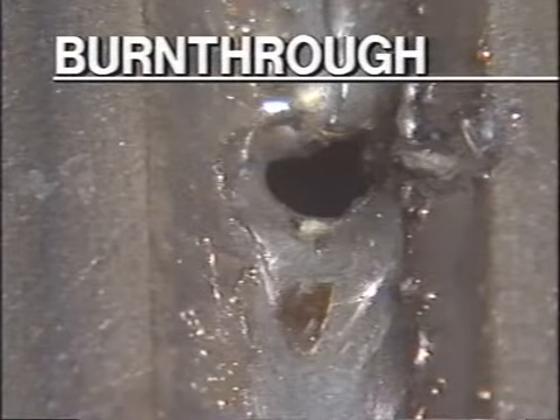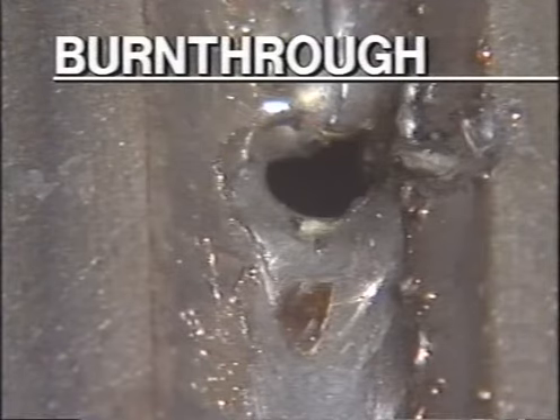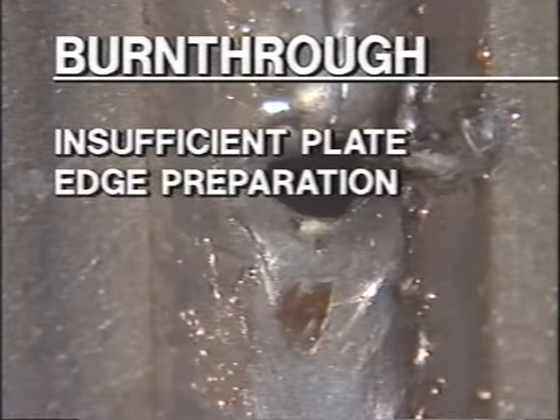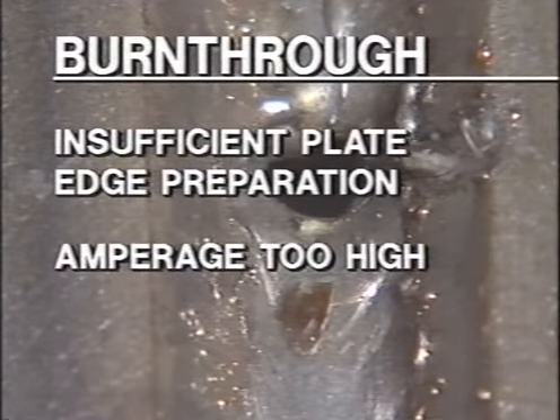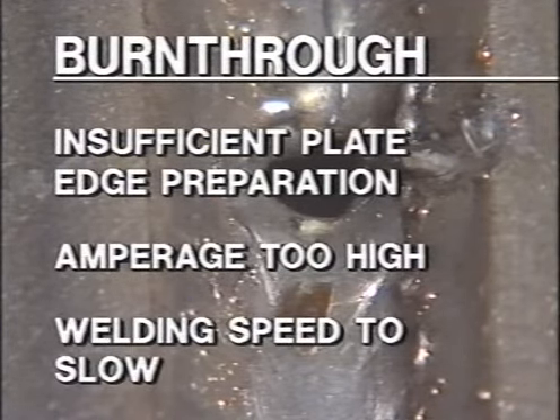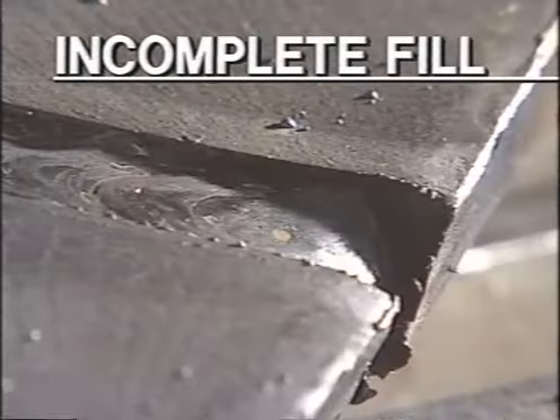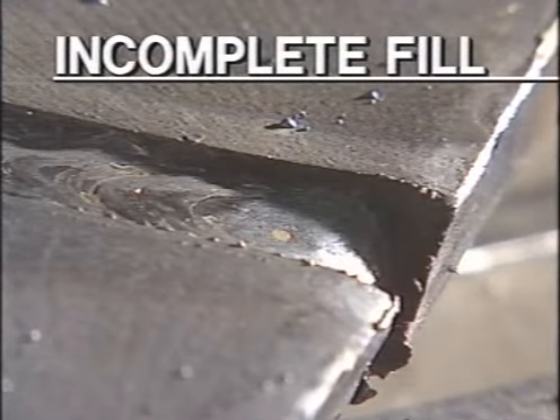A burn-through is exactly as it sounds. A hole in the weld bead occurs. This may be the result of insufficient plate edge preparation, amperage too high, or too slow a welding speed. Incomplete fill, on the other hand, results when the weld metal has not completely filled the joint between the parent metals.